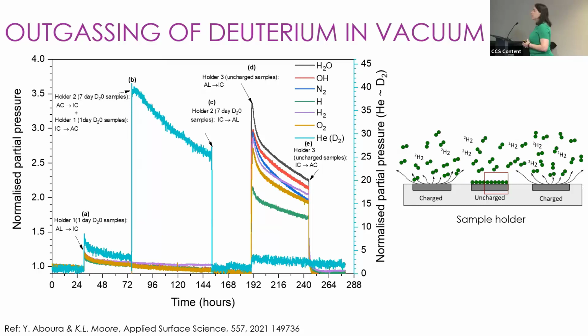Now, attached to the NanoSIMS, we have what we call a residual gas analyzer, and it allows us to determine the composition of the vacuum itself, so what compounds are in the vacuum. We have incredibly good vacuum, but there are still certain things in there. So what we did here, and I'm not going to go through the whole of this graph, but I just want to point out this time point here. This is where we introduced a deuterated sample into the chamber containing the residual gas analyzer, and you can see the deuterium signal shot up massively, dropped away over time, and then dropped massively as we removed that deuterated sample from that vacuum chamber.